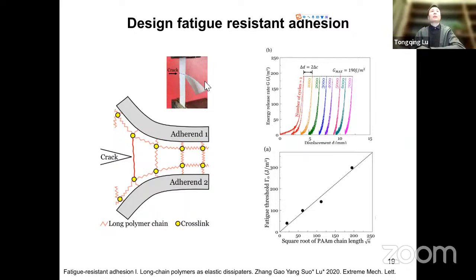Actually, when we prepare this kind of sample, we do the following. There is a top layer of cloth, which is nylon, and another layer of nylon cloth. We soak these two pieces of cloth in the precursor of the hydrogel. Before the hydrogel becomes solid, it is in a liquid state, and we soak them in the precursor and cross-link. Because the cloth has many microscopic holes, the polymer chains penetrate into the holes, so it forms an adherent structure naturally.